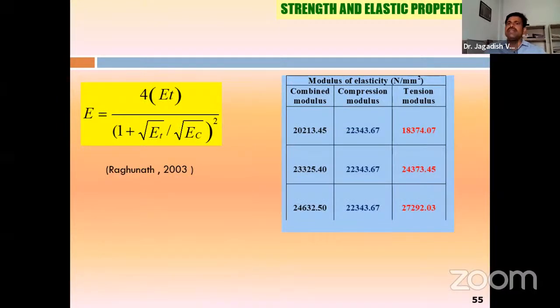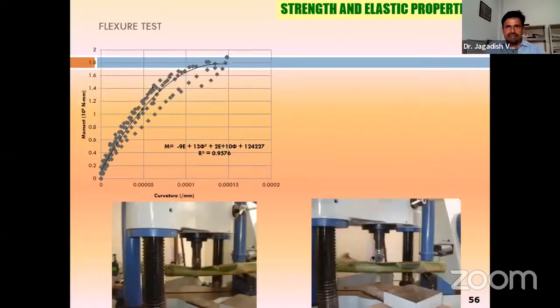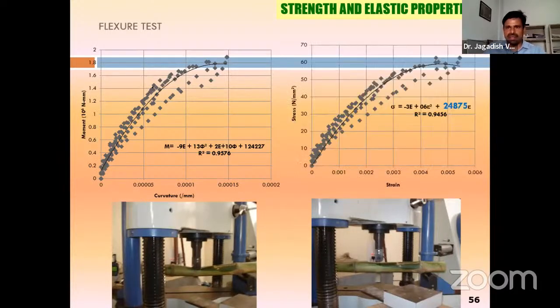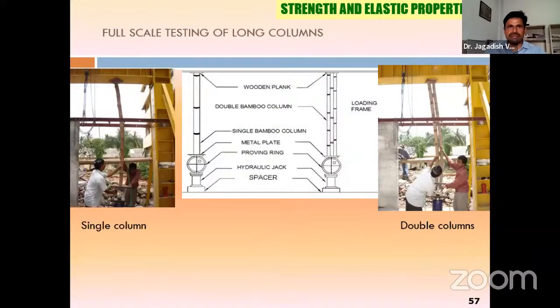You can find it. So anyway, we have already tested in the compression modulus using the compressive strength, so that you can get the tension modulus. So this is a very interesting test one can carry out to find out the combined modulus. Even the flexure, we have also carried out the flexural test, the typical values you can see, what we got.